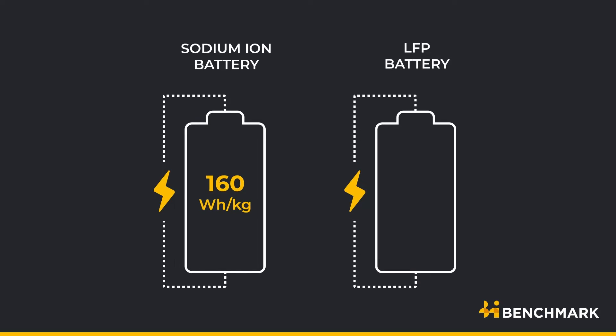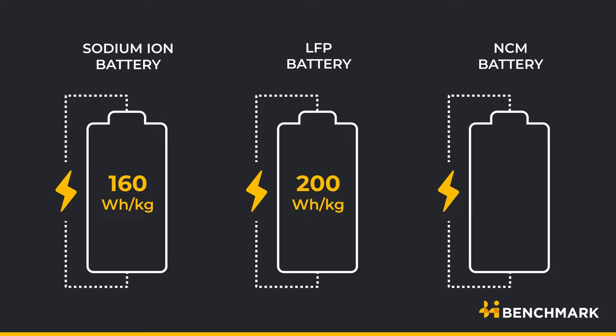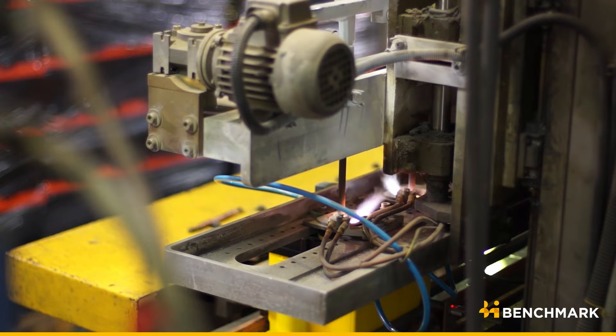The state-of-the-art sodium-ion batteries today do have a lower energy density than lithium-ion batteries. If you look at state-of-the-art chemistries, they sit at around 160 Wh per kg. Comparing that to something like LFP battery cells that sit around 200 Wh per kg, that's a 25% increase that's needed to come from cell design and manufacturing alone — and really, that's quite a big ask. When you look at the higher end of lithium-ion battery cell performance towards your high-nickel NCM chemistries, you're talking 260 Wh per kg at a minimum, and bridging that gap is really tough to do without serious innovation in materials chemistry.